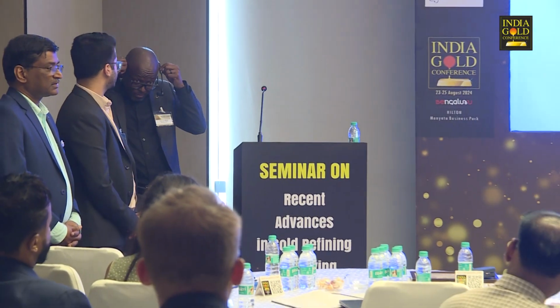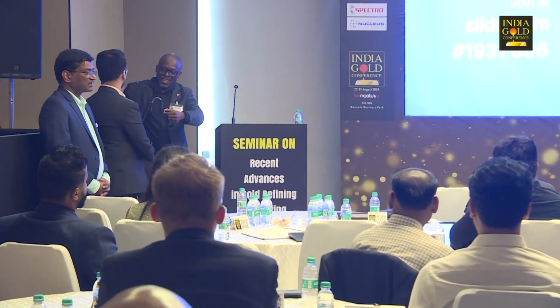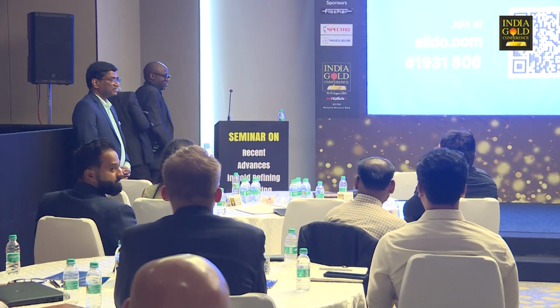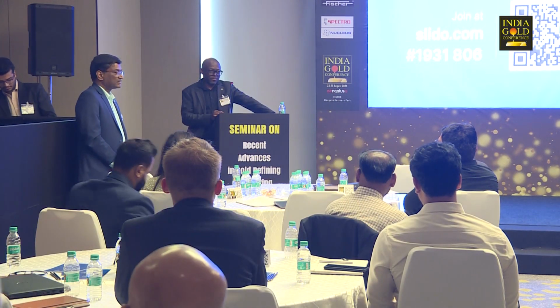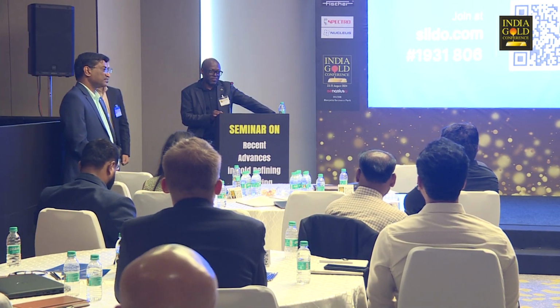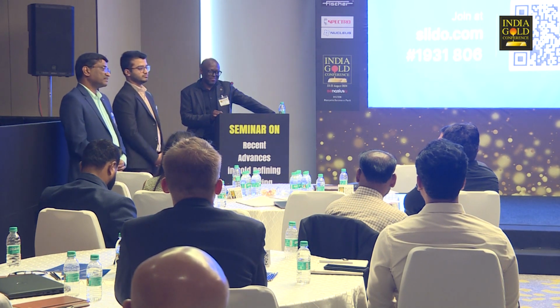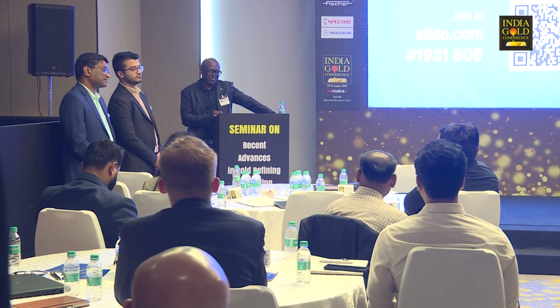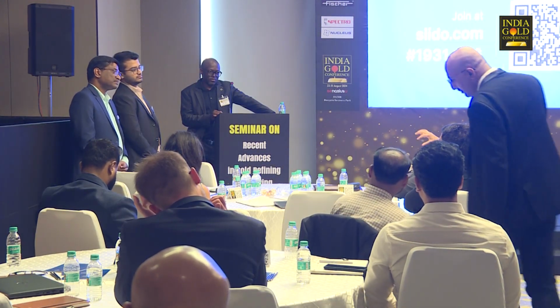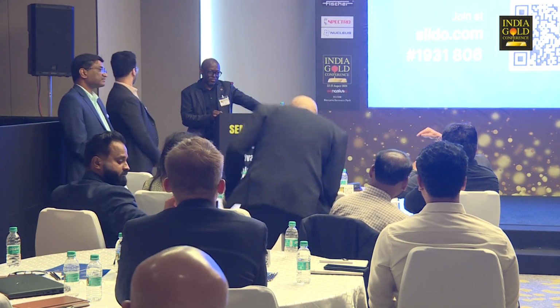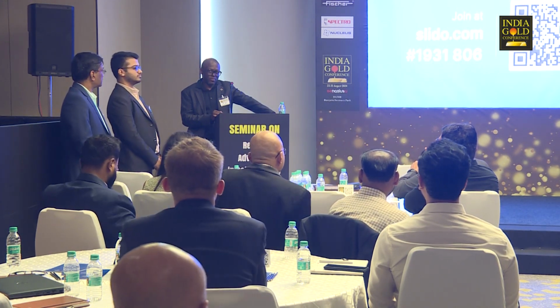Getting a sample, we follow a very different process where we melt the whole thing and test it by XRF. And if it is good quantity, then we follow what he has just said, either the dip sampling or taking the sample from the melt. What we get is maximum 1 kg, 2 kgs for the recycled gold. For the sampling, when we test with XRF, if you have an ingot, you test at 4 places at the top and 4 places at the bottom. And that's the sampling we do right now.